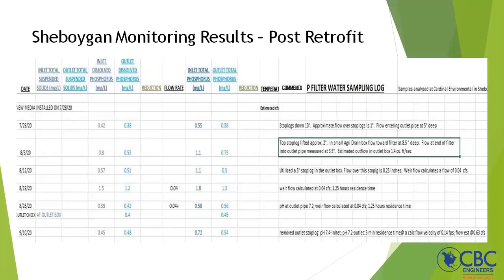After the blast furnace slag was put in, these are the results of the phosphorus removal. We're getting some, but it's not what I would expect. It's very low, but yes, it is removing some. I think we have to have at least a residence time in that case of probably at least an hour. And I think it's getting more like 10 minutes at most.